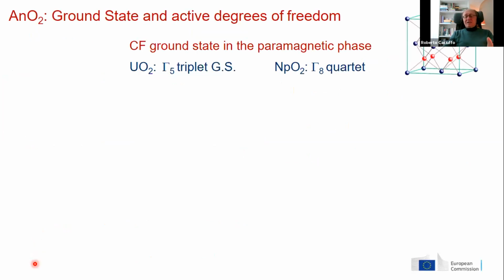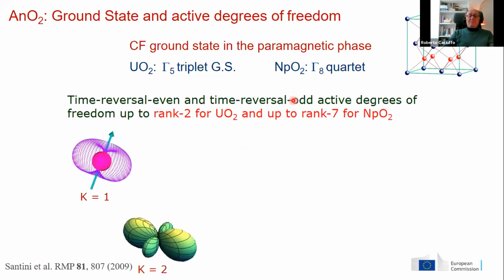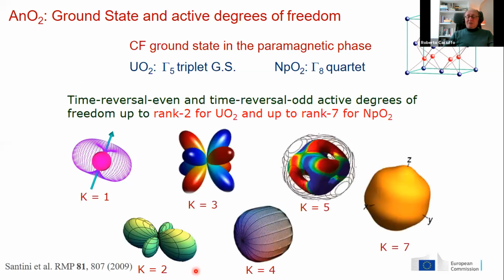Instead, important results have been obtained on the actinides. The important ingredient is the crystal field ground state, which in the case of uranium is a gamma-5 triplet. In the case of neptunium, it is a gamma-8 quartet. Now, the gamma-5 triplet supports magnetic dipole and electric quadrupole degrees of freedom. In the gamma-8 quartet, also octupoles, hexadecapole, triacontadipole, and rank 7 magnetic multipoles.